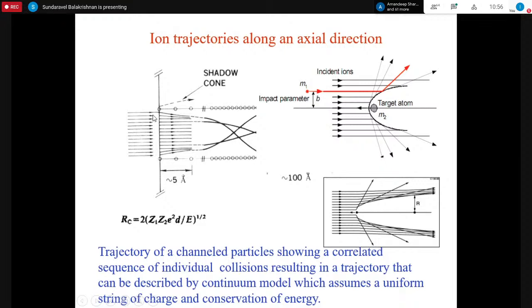And the radius of this shadow cone is given with this expression, and it is inversely proportional to E to the power half. So when energy is low, your shadow cone radius will be large, and when the shadow cone radius is large, for larger angles with respect to the incident axis also, you'll be able to get channeling. But once you go for higher energy, the shadow cone radius is much smaller, and even for a small tilt, it will get dechanneled.